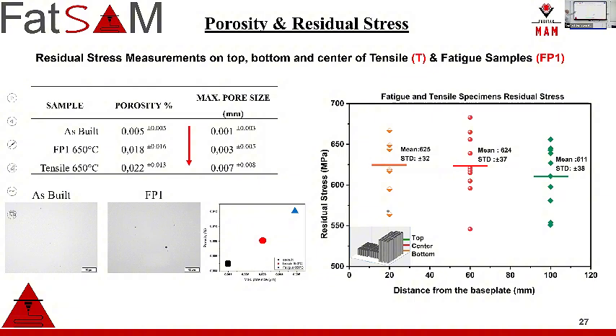Two comments. These are powder one. As I said before, including room temperature, four temperatures, 3 strain ratios. These are for the powder one, standard additive manufacturing procedures. But in the future studies, we have already started, and materials are produced. We are doing powder 2 and powder 3 as well. Powder 2 and powder 3 have higher VED value and lower VED value, which means higher porosity and lower residual stresses.